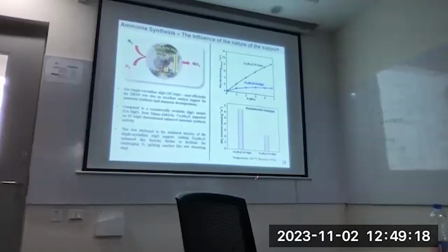Then we also tried photothermal ammonia synthesis. In this case, we used a xenon lamp, and here we can reduce the pressure. We can get the same activity. Here I have to use 50 bar to get 10 millimole of ammonia, whereas using photothermal ammonia synthesis, with a xenon lamp and only 10 bar of pressure and lower temperature also, we can get almost a similar amount of ammonia.